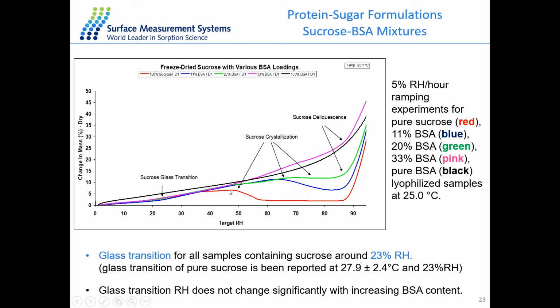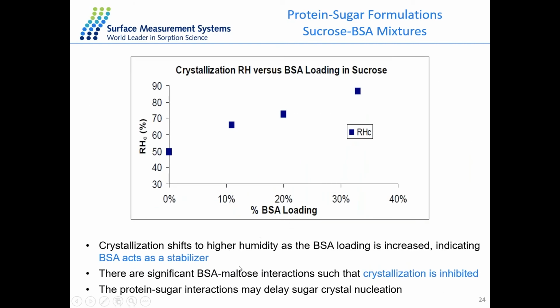As for the crystallization, the pure sucrose sample can crystallize at around 50% RH. And with the increasing of the protein concentration, this crystallization point is shifting to higher humidity, which means this protein can behave as a stabilizer to stabilize the mixture from the crystallization with the humidity. And this is probably because the protein-sugar interaction could delay the sugar crystal nucleation, and that will result in the inhibited crystallization. So here we can see the BSA protein is a really good stabilizer for the protein-sugar formulation with the interaction between the protein and the sugars. And DVS here could demonstrate this kind of influence of the protein concentration on the stability against vapor-induced phase change.